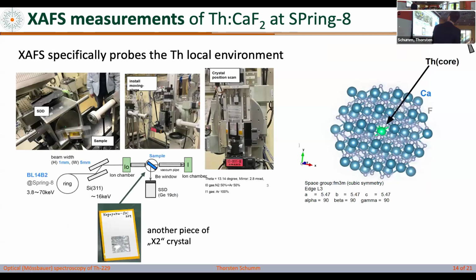And we found such a method. It's called XAFS. It's X-ray absorption fine structure spectroscopy. So what you do is you again use the SPring-8 synchrotron, and you tune it to a 16 keV line, which is the inner shell L-shell electron of thorium. So that means you are energy selective. You ionize only thorium in the calcium fluoride, and the calcium and the fluoride is completely invisible in this material at these wavelengths.